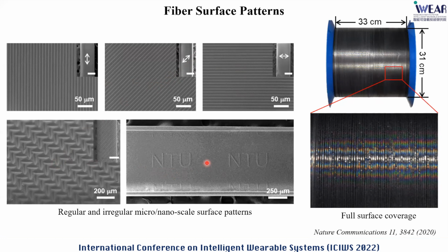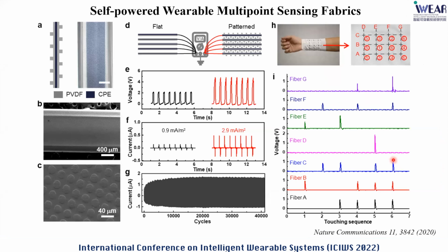And this process is continuous. And here shows that, for example, this spool of fiber has a length of about 300 meters. And here is the zoomed-in photo of this one. You see those beautiful color patterns, indicating that the surface of this 300-meter fiber is fully covered with those nanostructures. Then to use them for wearable applications, we weave them into fabric to make them into self-powered sensing. And here we have 3x4 fibers, and they form those 12 detection points to measure the pressure here.